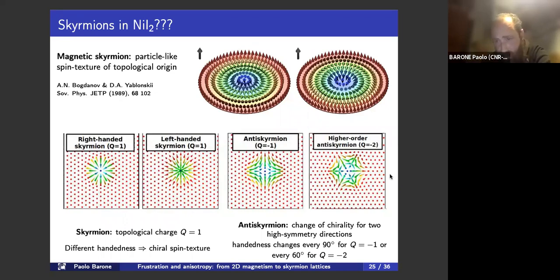And what I wanted to show here is the spin texture of this Q equal 2 anti-skyrmion. So this is like the Q equal 1 anti-skyrmion, but it's characterized by the fact that it's multi-chiral. So there is a change of chirality of the handedness of the in-plane texture when moving around this high symmetry direction. And this looks very similar to what we found in our simulations.